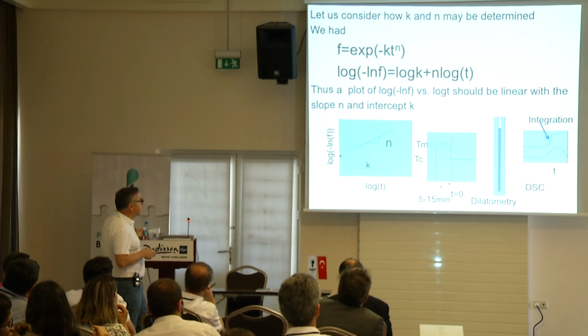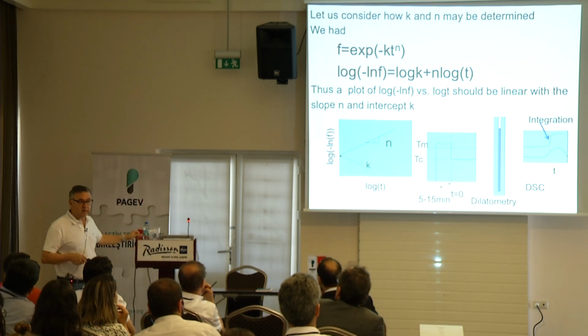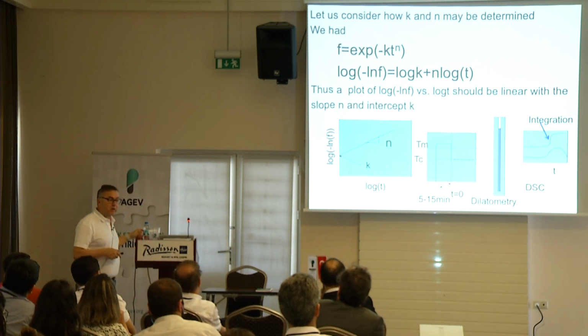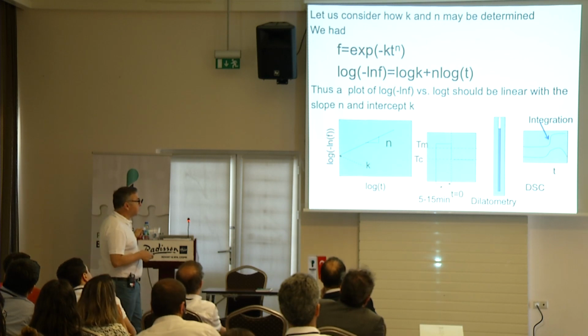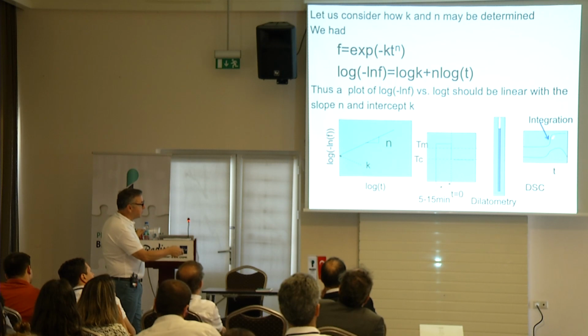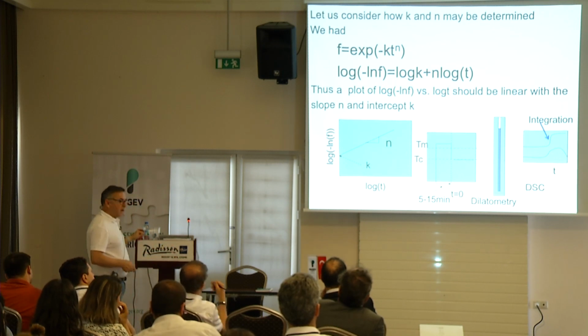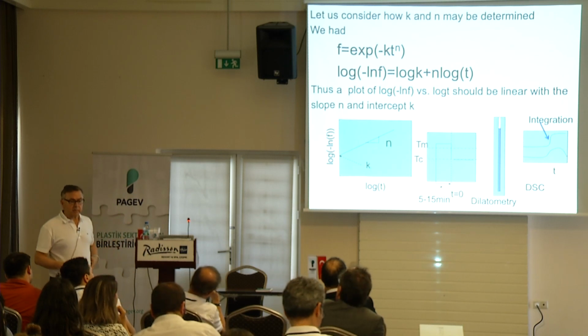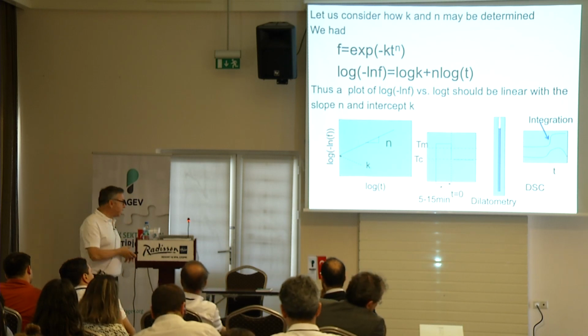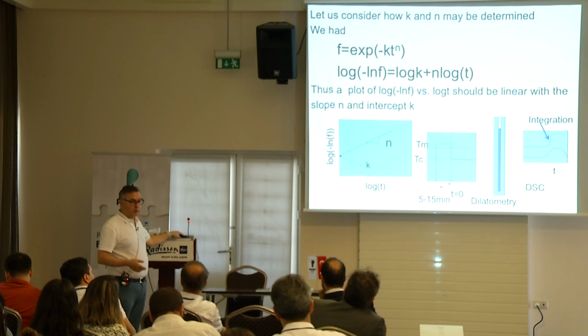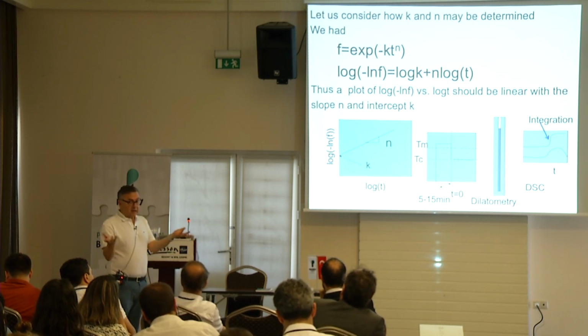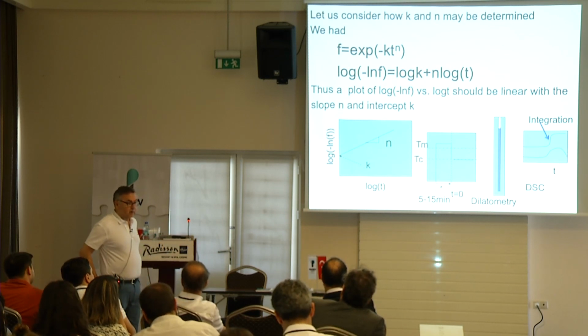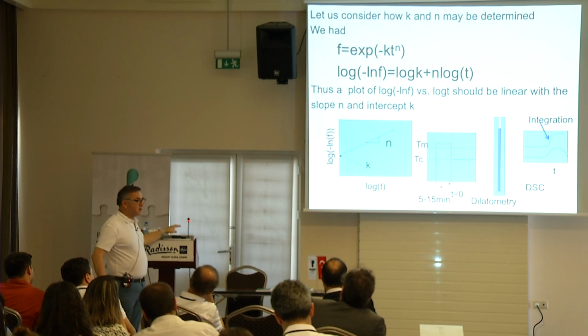In fact, if you buy any differential scanning calorimetry, nowadays software comes with it. You can do this on a differential scanning calorimetry, which gives you the crystallization profile. You just simply do a partial integration and get the same equation, and so on. This is fairly well established in industry. If you have a differential scanning calorimetry and you're not using it for your processing applications, you're not using your DSC. It's very powerful because these kinetic parameters are influenced by a whole bunch of things.